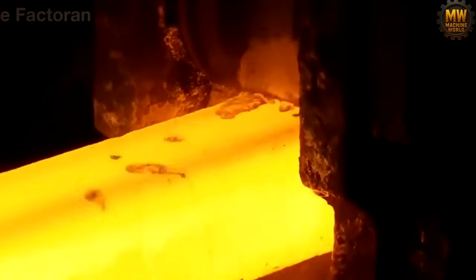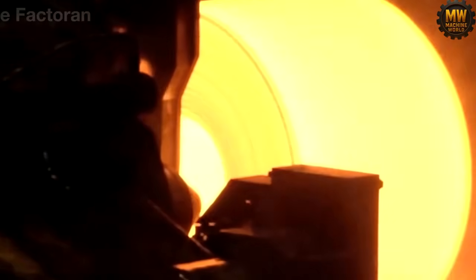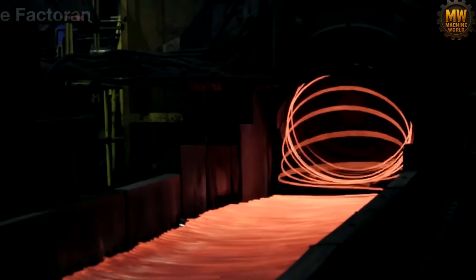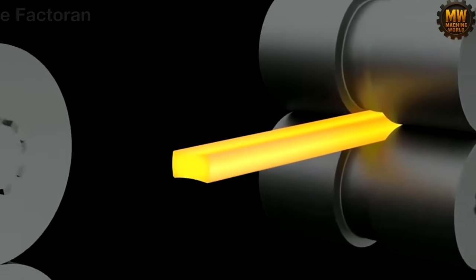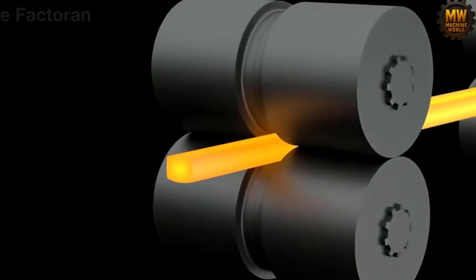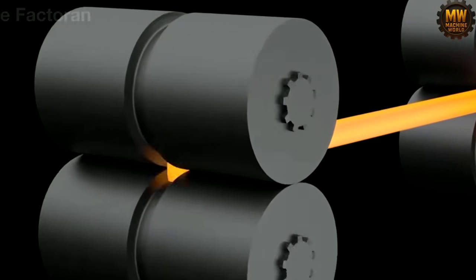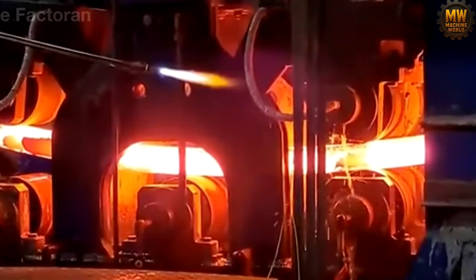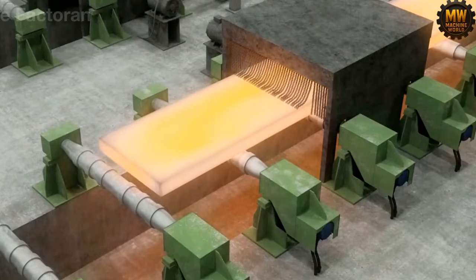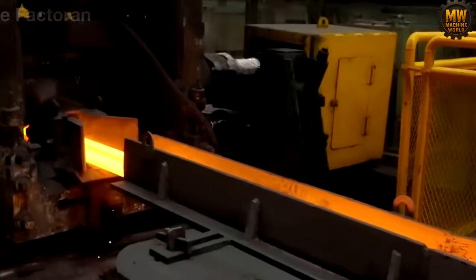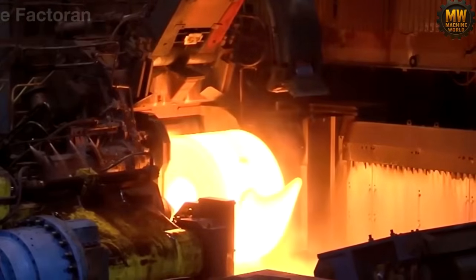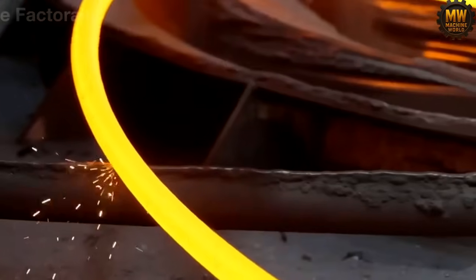Burning billets fly from the casting floor straight into the ruthless jaws of the hot rolling mill. The air trembles and blurs from the sheer fiery heat, carrying the dull, heavy hum of compressed steel. An incandescent block slams into the continuously rotating rollers. The gap violently shrinks. With a deafening crunch, the dense steel is forcibly squeezed and stretched into a long, luminous ribbon. At roughly 1,200 degrees Celsius, the metal remains entirely ductile.